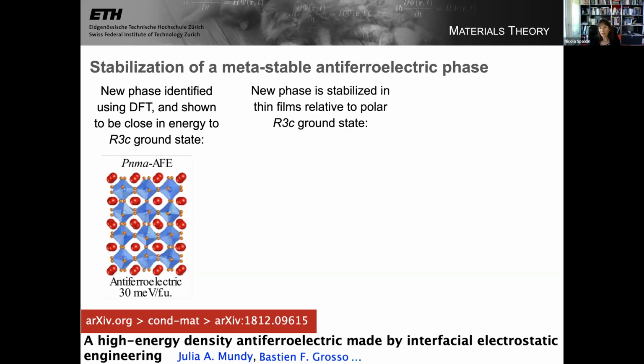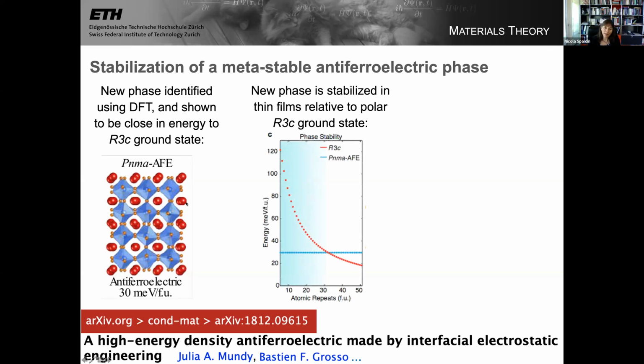And then he was also able to show, using a simple electrostatic model, that if your film is thin enough, so here he's plotting the energy in millielectron volts per formula unit as a function of atomic repeat units. So a bismuth oxygen layer plus an FeO2 layer. For the R3C structure, which is ferroelectric and has this problem with the surface charges, and for his new structure, which I'll show in a moment, is anti-ferroelectric, so it doesn't have any surface charge. And so the R3C structure, the ferroelectric structure, its energy goes up and up and up as it gets thinner because of the unfavorable electrostatics. But this non-polar structure doesn't care about getting thinner because it doesn't have any surface charge. And so below a certain thickness, it becomes the stable phase.